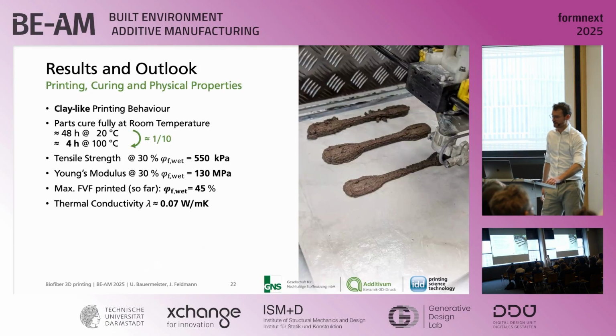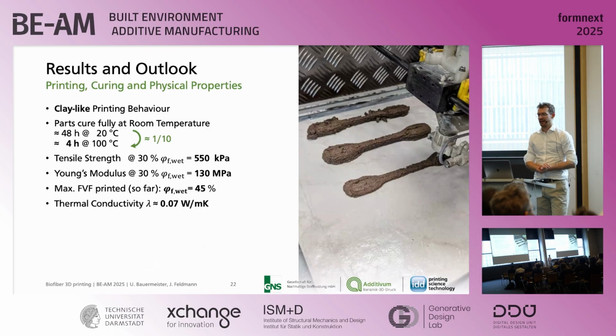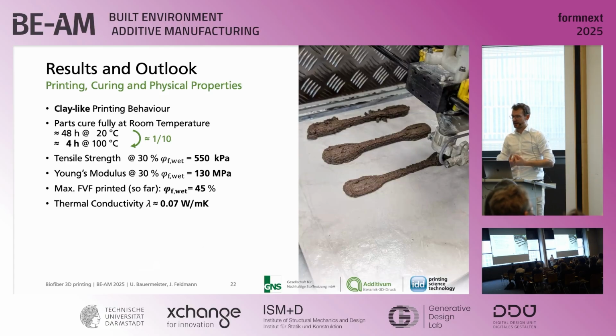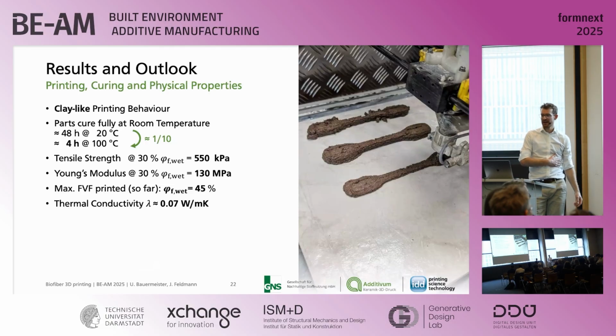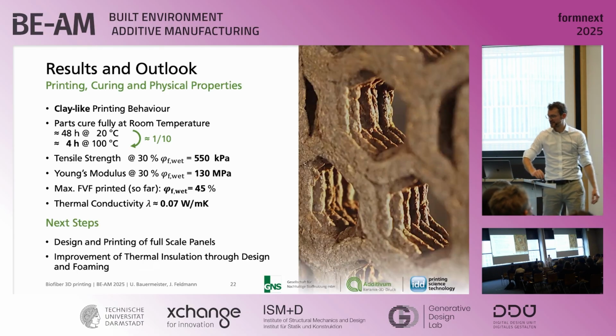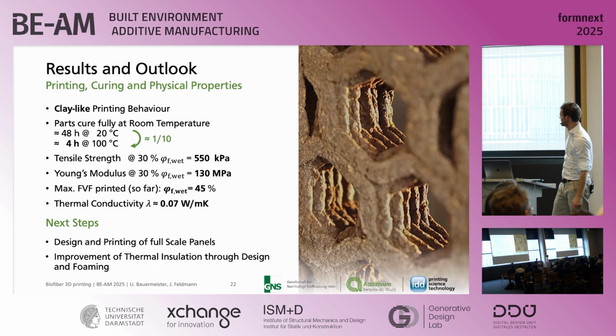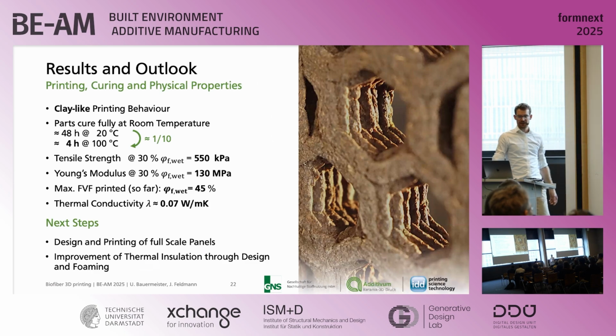Quick summary on the material itself. We have a clay-like printing behavior we could achieve. Drying usually takes about 2 days. It depends a bit on the thickness of the material, but we can speed up the process by a lot by just applying heat, 100 degrees here, for example, 4 hours for a sample part. Tensile strength and Young's modulus is not great yet. I would compare this to firm-ish XPS foam, but this is also a sample with a fiber volume fraction of 30%, and we achieved to print with higher volume fractions of 45 to 50%, which made the parts much, much stronger. And also thermal conductivity is all right, but it's not as good as we wanted. So next steps is to look into designs of large-scale panels and improve especially the thermal insulation through design and foaming.